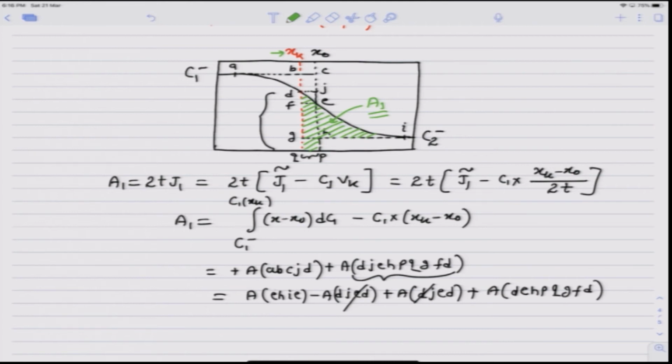This was about binary intrinsic diffusion. Now, if I want to evaluate the ternary intrinsic diffusion coefficient, it is much more difficult because we need at least two diffusion couples yielding the marker location at the same composition, which is almost not possible to obtain.